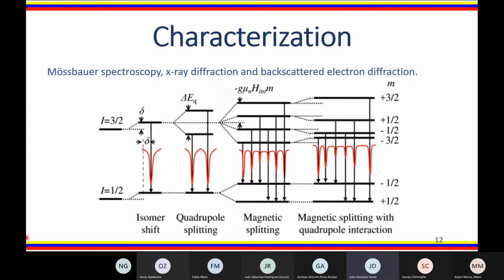To characterize these alloys, we have used different techniques, including Mössbauer spectroscopy, X-ray diffraction, and backscatter electron diffraction. In the case of Mössbauer spectroscopy, there are three types of hyperfine interactions. The first is isomer shift. You can see a singlet, in this case, one peak in the spectra. The second, the quadrupole splitting, you can see a doublet, in this case, two peaks in the spectra. And finally, hyperfine field with 6 peaks in the spectrum, in this case, one sextet. These three interactions characterize the chemical environment of iron atoms.